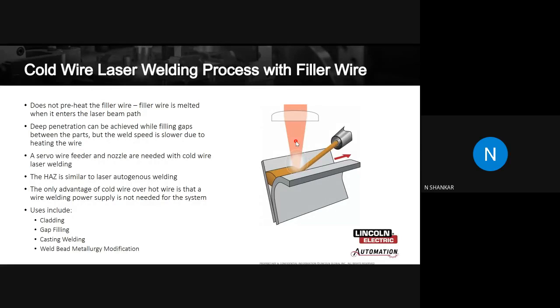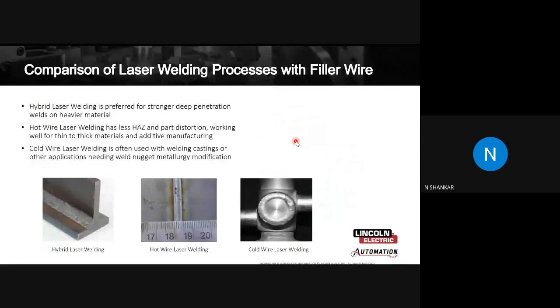The only advantage with the cold wire over hot wire is that the wire welding power supply is not required here. In a hot wire, you need a welding power source to heat the wire or preheat the wire, which is not required here when you do a cold wire filling. This also finds use in cladding applications wherever gap filling is required and welding of cast parts is required. This again is a good process.